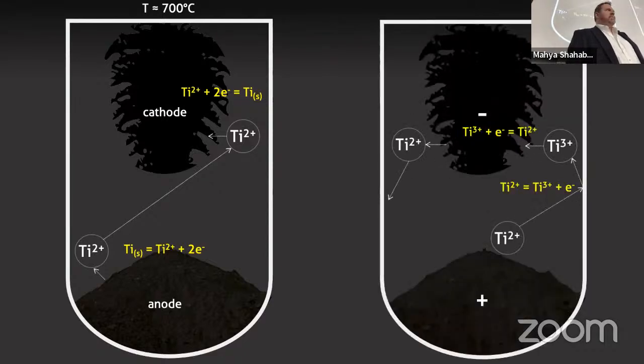I think folks will immediately see the issue: you have this redox looping, a current inefficiency problem that comes from having both the 3+ and 2+ options. You can have some of the 2+ go to the wall instead of the cathode, and it can then get further oxidized. That further oxidized one can then turn back into 2+, and you can have a low current efficiency. Overall, the current efficiency of the system is typically somewhere in the 60 to 70% range.